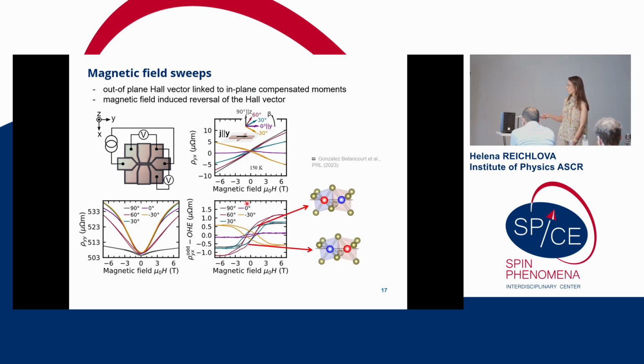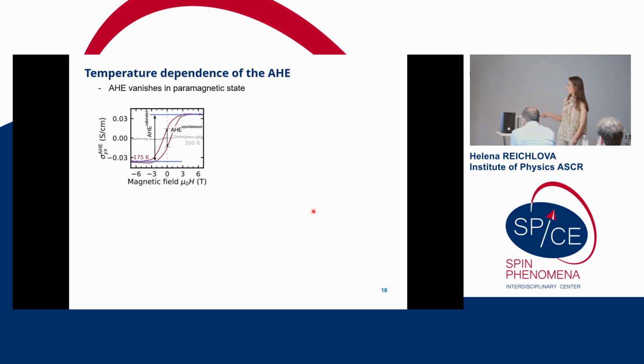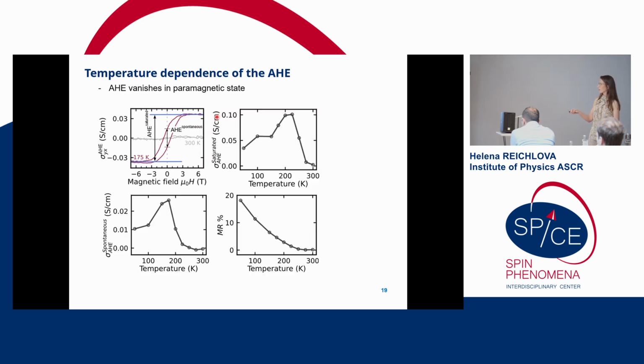And now, the suggestion is that this indeed corresponds to two opposite Néel vectors of the manganese telluride. When we take one of these anomalous Hall curves, we define something which we call the spontaneous anomalous Hall effect, which is present in zero field and saturating, and we can plot it against the temperature. We can see that indeed it's present in the full temperature range until, let's say, room temperature, which is also the critical temperature of our manganese telluride.